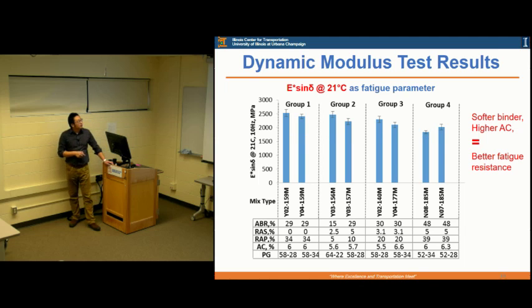So when we put all the mixes together, we cannot easily do comparison. So we just put them into different groups. For example, if you look at group 2, comparing these two mixes, you find that 157 had a lower E star times phase angle than 156, which means this one has a better fatigue resistance.